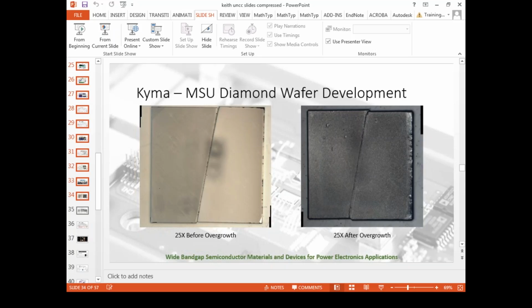And they said, so there's maybe 3 ways that one could get large area electronic grade diamond. One is to slice layers from that bulk 7mm sample and stitch them together. So here we took a 7mm by 7mm approximately wafer and intentionally cut it and cleaned up the edges a bit and put them next to each other and grew over it. And so here's after we grew over it to see if we could prove that you could make these things stick together.